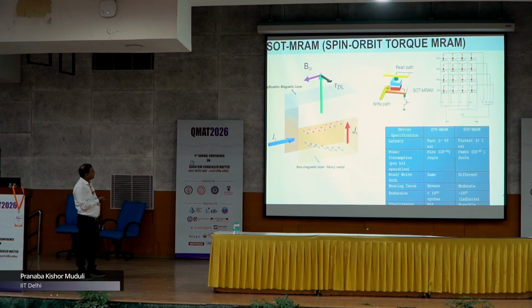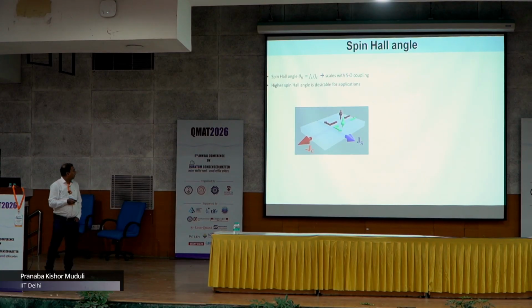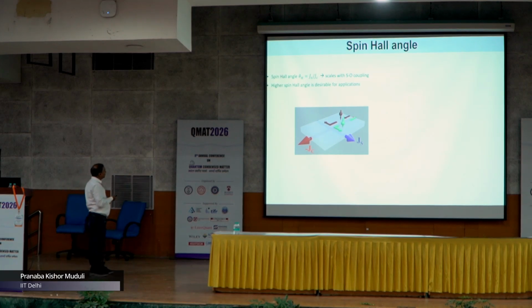You can make a cross-bar structure like that, and the advantage of this compared to the so-called STT-MRAM, where you use two magnetic layers, is that this is much faster, and especially the endurance is much higher in this case. So this is the motivation for this. However, before we realize this, we need to improve the efficiency at which you are generating the spin current, and this efficiency is determined by the spin Hall angle, which is the ratio of the spin current to charge current. It scales with the spin orbit coupling, and you need to have higher efficiency.